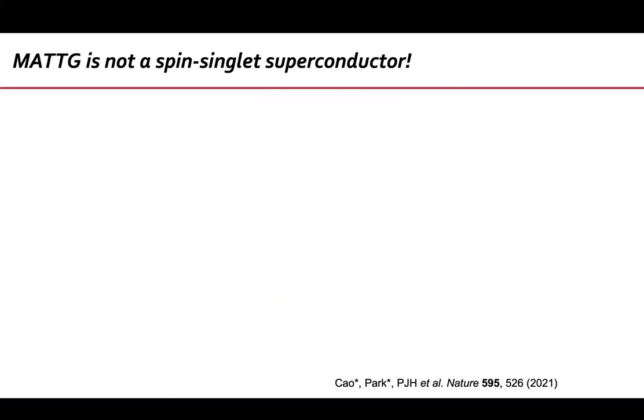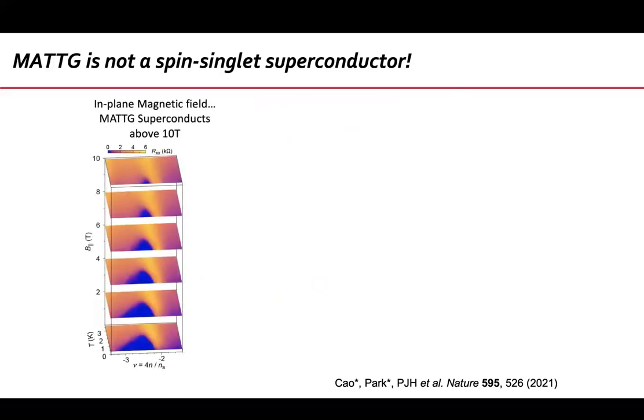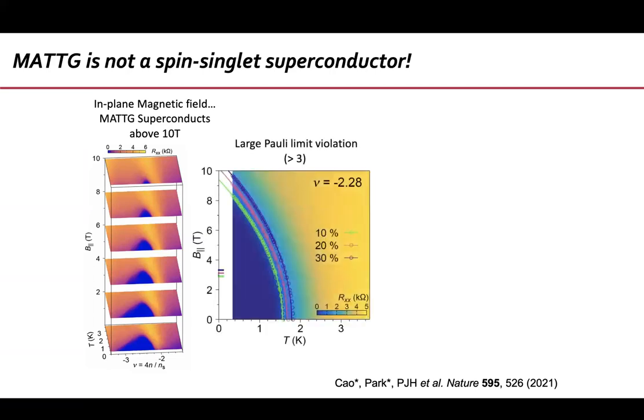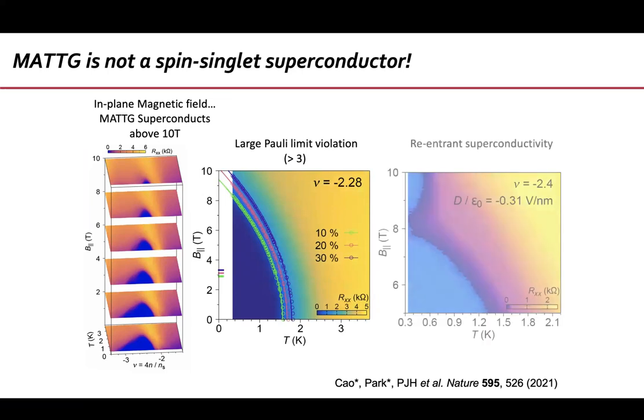So twisted trilayer graphene is not a spin singlet superconductor. Okay. If you apply an in-plane magnetic field to the system, which is 2D, okay? You apply an in-plane magnetic field, you can go to magnetic fields way above the Pauli limit and still maintain superconductivity, okay? You can do this continuously, you will violate the Pauli limit by over a factor of 3. This is in a system that doesn't have spin-orbit coupling, et cetera, okay? In fact, not only can we violate the Pauli limit by a lot, we can kill superconductivity and then see it re-entering, okay? You apply a higher magnetic field and superconductivity comes back in. Yeah. Yesterday you told us that valley and spin were both with degeneracy. So if it's not spin singlet, then it's symmetric in spin space.